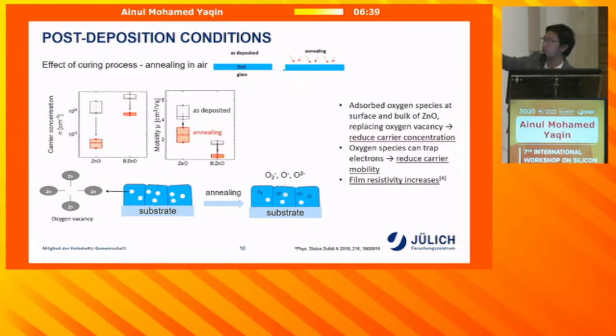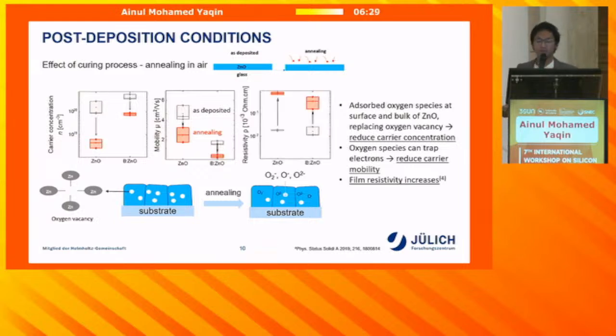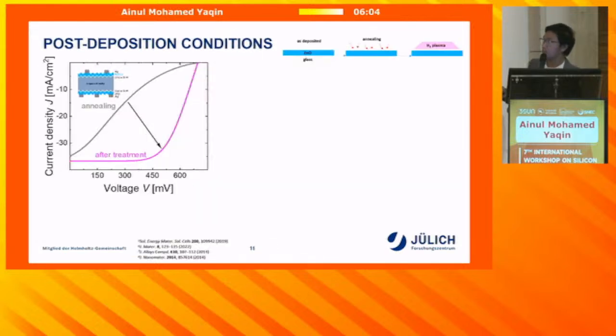Also, these oxygen species in the film can trap the electrons, which limits the mobility of our film, as shown here, and results in the film resistivity increasing by 1 to 2 orders of magnitude, which is not great. There are several ways to mitigate the issue. For example, we can add a capping layer to protect the PECVD TCO, or we could process with some extra treatment. What we did was a hydrogen plasma treatment right after annealing. Here we show the improvement, which eventually improved the solar cells, especially the fill factor.